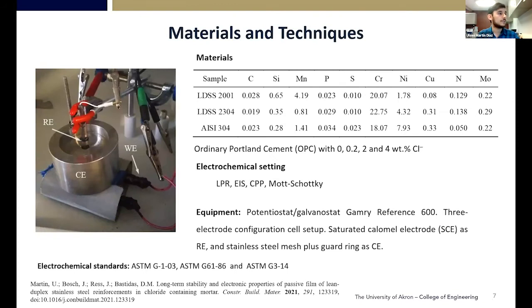As we see here, we have the 3 different alloy compositions. We used some concrete mortar contaminated samples with 0, 0.2, 2, and 4% weight chloride per weight of cement, where we applied some different electrochemical settings to see how this passive film was evolving and what the corrosion properties were.